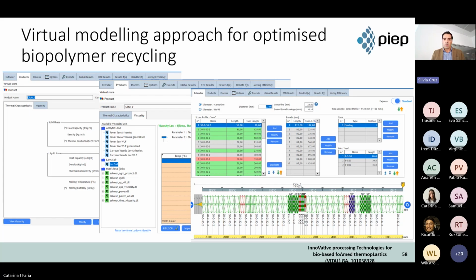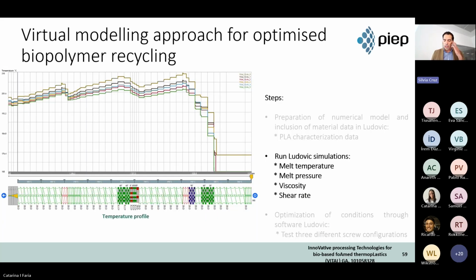With all this data in, we run the simulations, and what we get is, I would say, as expected. In the graphic that you see, we have the behaviors of the 5 different materials with different cycles of reprocessing. And we observe immediately that the melt temperature is decreasing with the reprocessing cycles of the material. So it's a clear indication that the chains of the material are being broken. So there is some degradation, and the viscosity is getting lower. That's why we get lower melt temperatures.